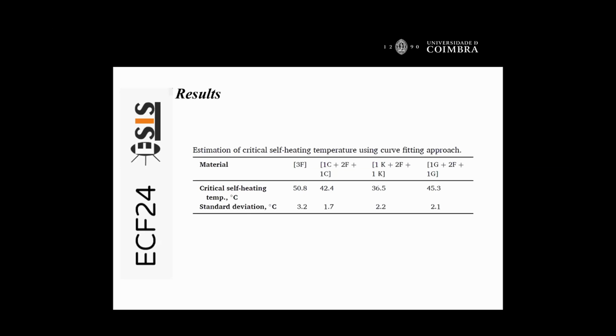Okay, this is not new, but it confirms that this strategy can be applied to hybrid laminates, and we can also observe that there is an influence of the constituents. In this case, we maintain the resin constant, but we change and combine different fibers. And here we can observe the influence of the fibers. Okay, but it is necessary to confirm these values.